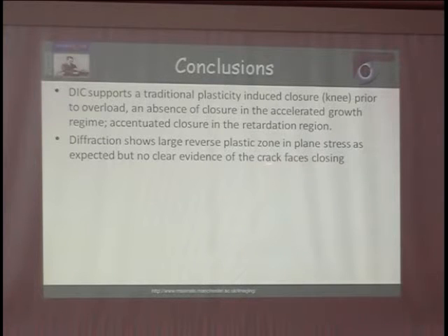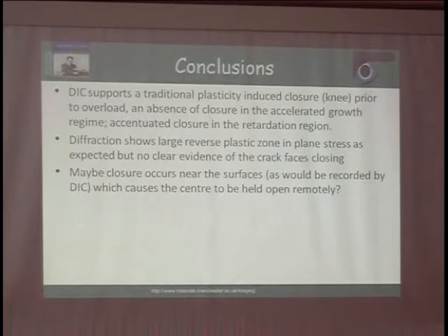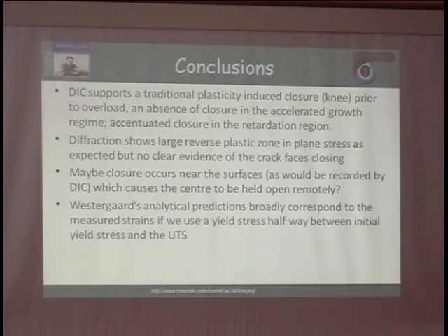Why do we not see crack faces closing and a large compressive stress? Maybe the closure occurs at the surface of the sample, and that's holding the sample open. It's certainly true that we see tension behind the crack. So after unloading, we see significant tension ahead of the crack, but we don't see any compression relating to crack face closure behind the crack.